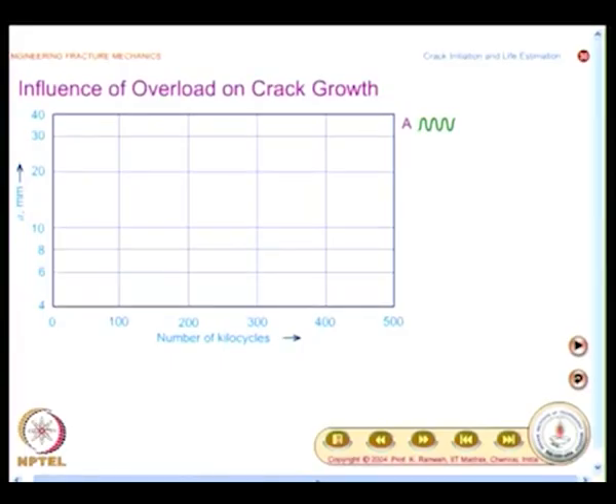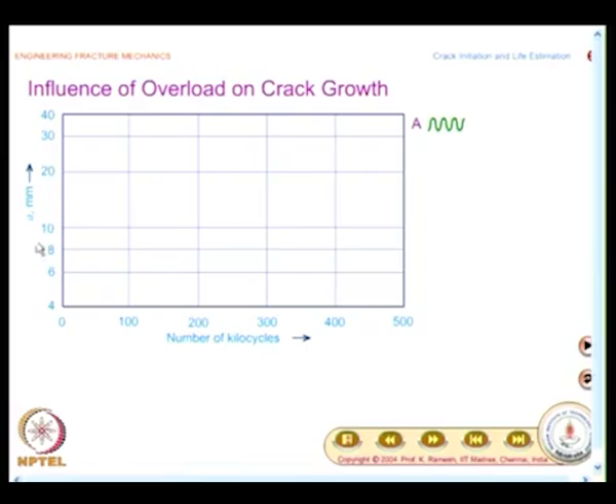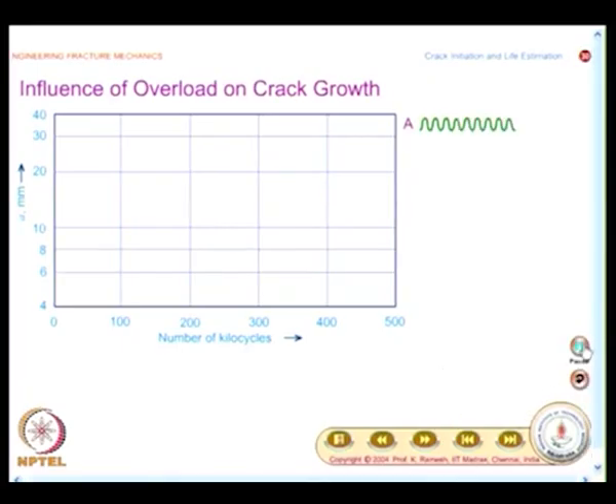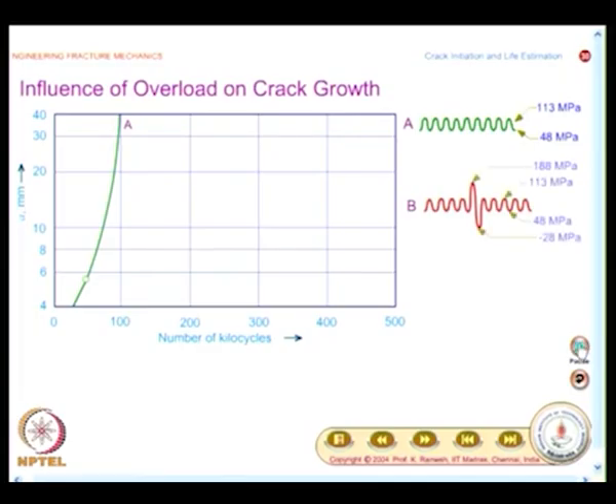at periodic intervals. People have observed from actual practice that it has helped the life of the structure, and you will have a proof based on plastic deformation that overload really helps, and overload of what kind, that is another question. Okay. So, we will look at a graph like this. On the x axis you have the number of kilocycles, on the y axis the length of the crack is put, it is a log graph on the y axis, and initially you take a constant amplitude, and let us see how the crack growth for this case is. You also have some numbers given to this, it is varying from 48 MPa to 113 MPa, and you find the crack growth is something like this.